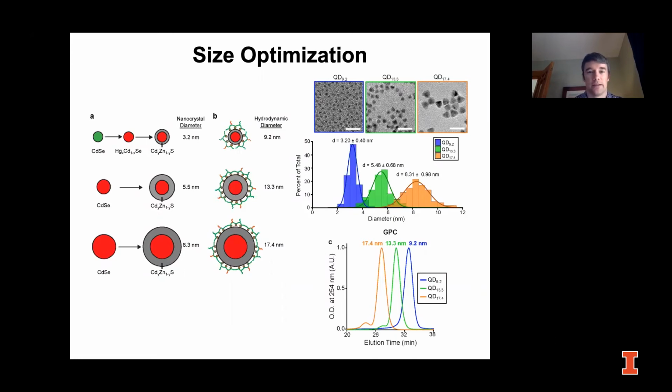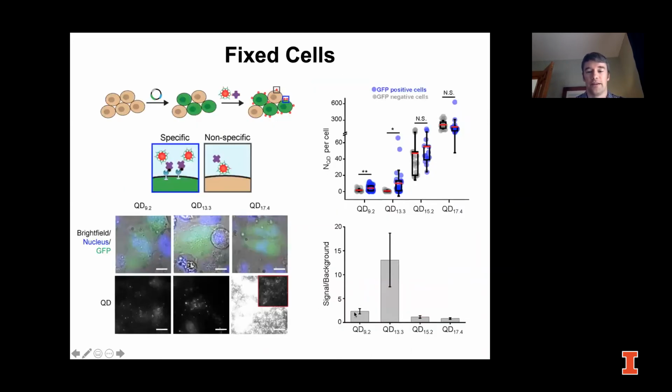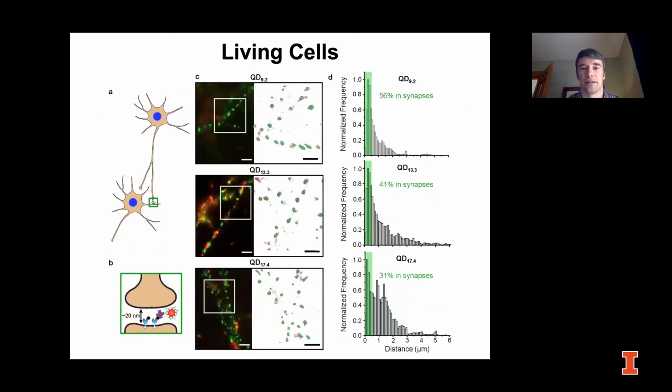You lose, many of the quantum dots are not emitting anymore. Many of them are off, meaning that they don't emit light. And also, they seem to be more susceptible to their surroundings, like acid. In some contexts, if they're exposed to acid, they'll degrade. So we're still trying to improve these, and we still think we can make these even better than what we have right now. However, they're very satisfactory for labeling living cells.